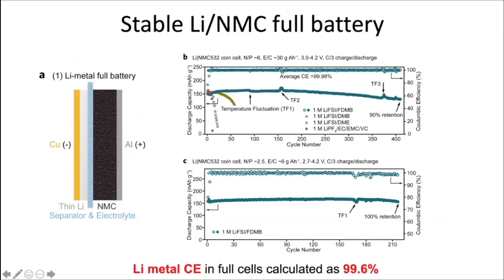So here we build the full cells with lithium metal on one side. And this is a thin lithium metal. We tested 25 micron lithium metal and NMC as the cathode. So this is the high voltage cathode. And the full cell Coulombic efficiency we can achieve is one of the best reported in literature, 99.6%, and with a very good capacity retention here, even after 400 cycles.